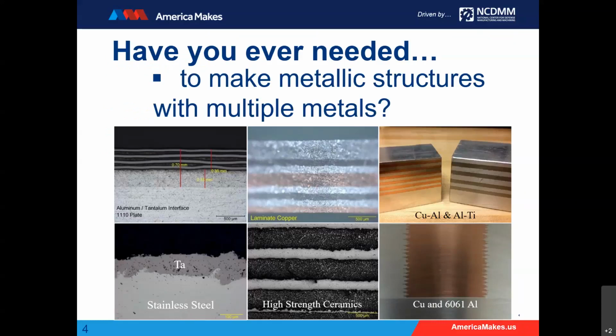So a little bit about ultrasonic additive. We're a 3D printing process, but our major difference is instead of using powders or wires, we're using thin metal foils. And instead of melting those feedstocks, we're actually welding them in the solid state at essentially room temperature. The way we do that is with ultrasound, and I'll explain that later. But some of the differences that evolve from doing this at room temperature enable us to make parts that you just couldn't make with other manufacturing technologies.